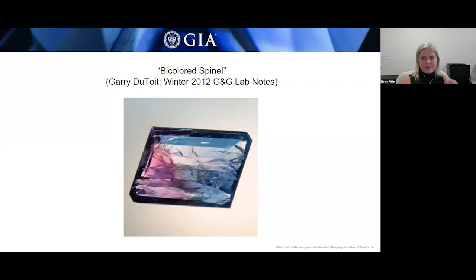Microscopic examination did reveal natural inclusions, and with the aid of Raman spectroscopy, there were no indications that the stone saw any heat treatment to alter the color of this stone. There was also no indication of dye present on either side. And so the gemologists collected UV visible spectra on both sides to determine the cause of color. The blue side had absorption features caused by the presence of iron, while the red side had absorption features caused by the presence of chromium.